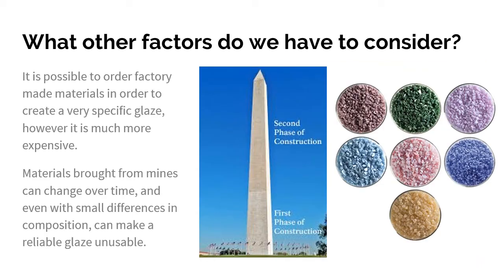Some of the things to consider, because those raw materials are coming from mines, if the mine opens a new vein, or if they dig far enough, there could be a change in composition. So an example would be our very own Washington Monument in DC. All of the materials for the Washington Monument came from the same quarry. The difference is that the Washington Monument started to be built, and then they ran out of money, and it sat there for a very long time not being finished. Eventually, funds were raised to finish the monument, but there is that noticeable color difference. And that's because the raw materials from the mine changed very slightly in composition. So they kept digging through the quarry, and so that material now has a slightly different color to it.